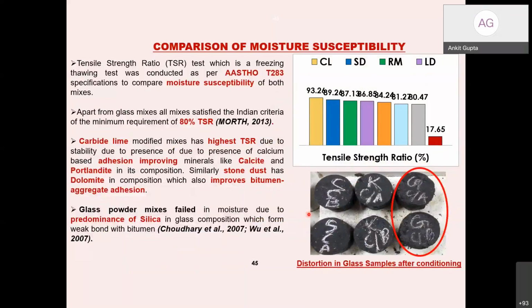Now coming to the next test, which is the moisture susceptibility, done as a tensile strength ratio, that is the TSR test as per the AASHTO T283 specifications. There is a fixed value that the minimum requirement for this TSR should be 80%, and it is given in the Indian guidelines. Now the carbide lime modified mixes have the highest TSR value.